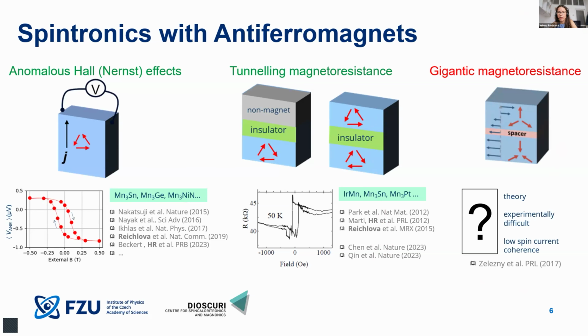one of the hallmark effects of spintronic research is the giant magnetoresistance, which is basically the equivalent of the tunneling magnetoresistance. However, in this case, we have a simpler structure and we rely on a non-magnetic conductive spacer, such as copper. And here we really probe directly the spin polarization which comes from one magnetic layer and how it is deflected or absorbed in the second magnetic layer. And this giant magnetoresistance effect was explored theoretically in antiferromagnetic systems. There is a beautiful paper of Jakub Železný and others.